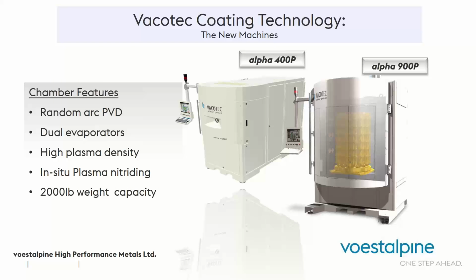So let's see, what's the next? Okay, we have an example of our coating chambers. The one on the left here is our Alpha 400, and this is a 900. Basically, the numbers are designations based on the size of the chamber. So all our chambers are random arc PVD. And the random arc is basically a process where we apply an arc to, you'll see it here in the large chamber, these two round puck-like things. That's our cathodes, and we apply an arc to those cathodes under vacuum and temperature. These pure metal alloy targets or cathodes, they vaporize into a plasma field. And the dual targets, as you see here, dual evaporators, they allow us to create complex and interesting chemistries with different properties.